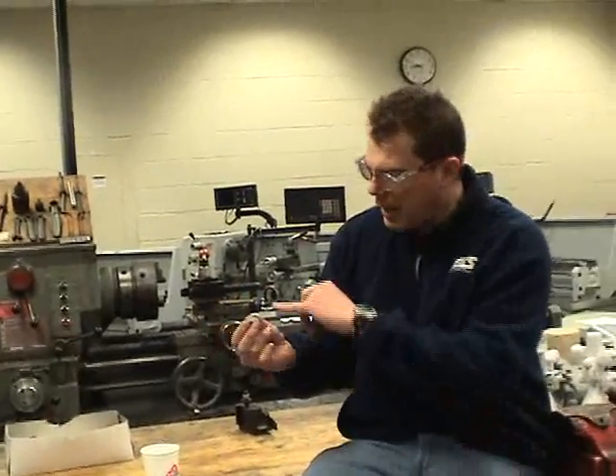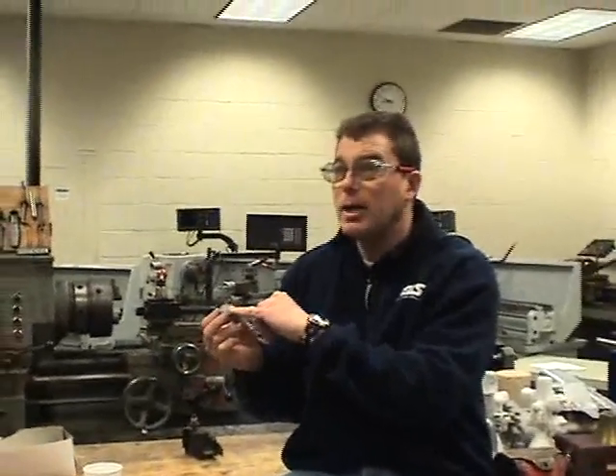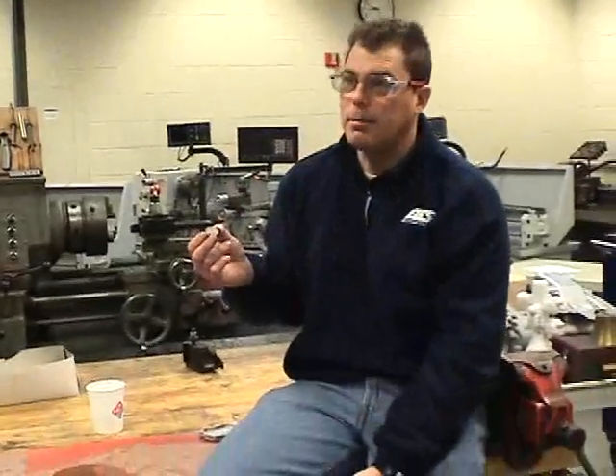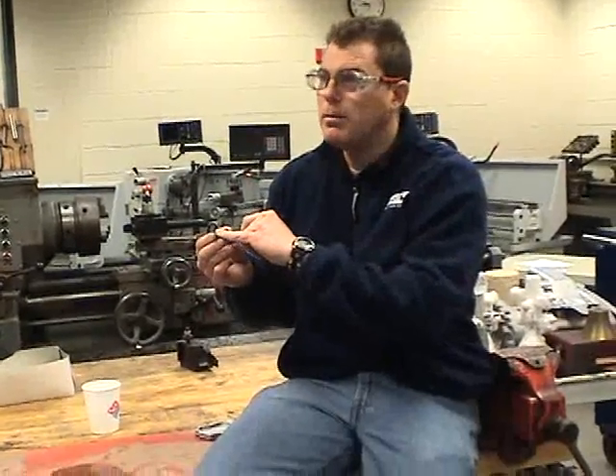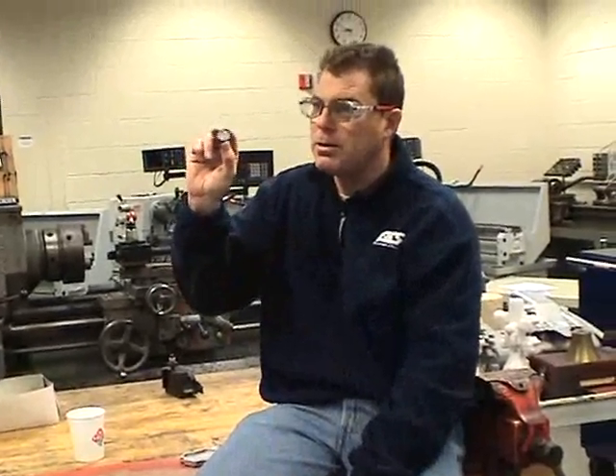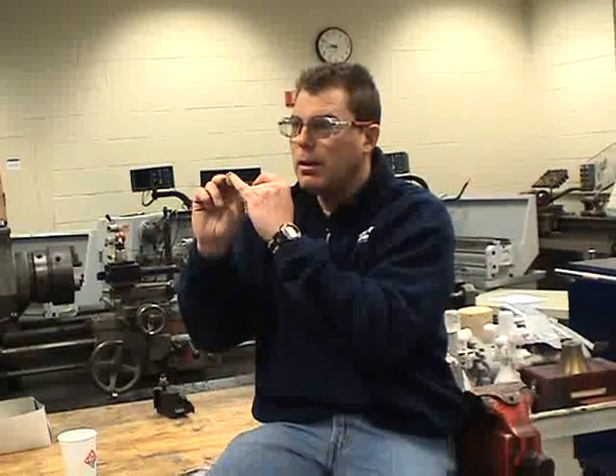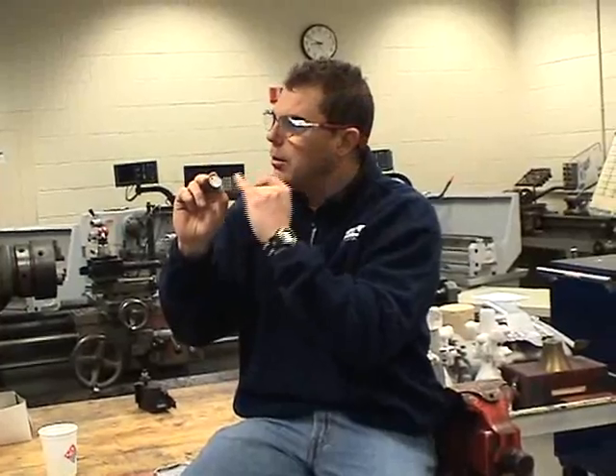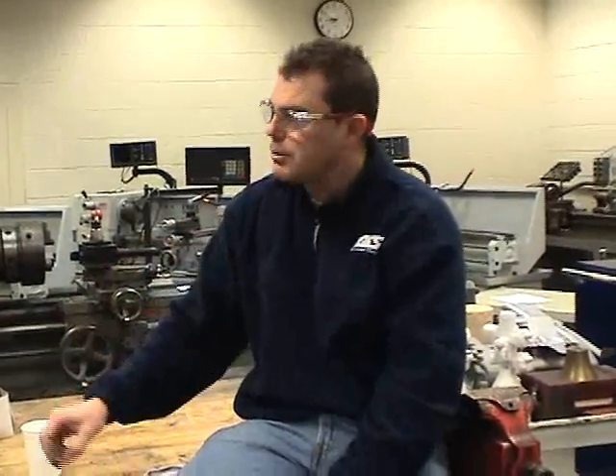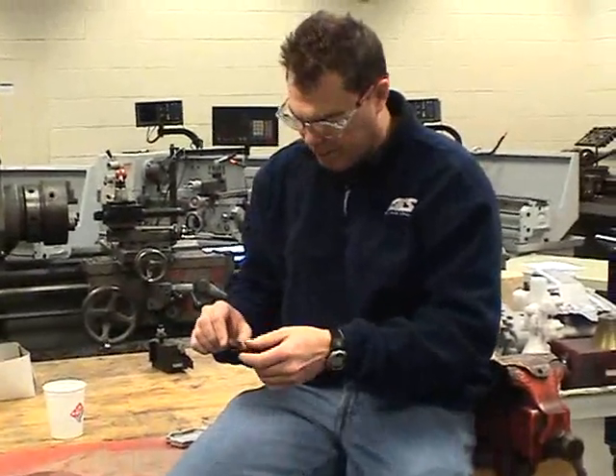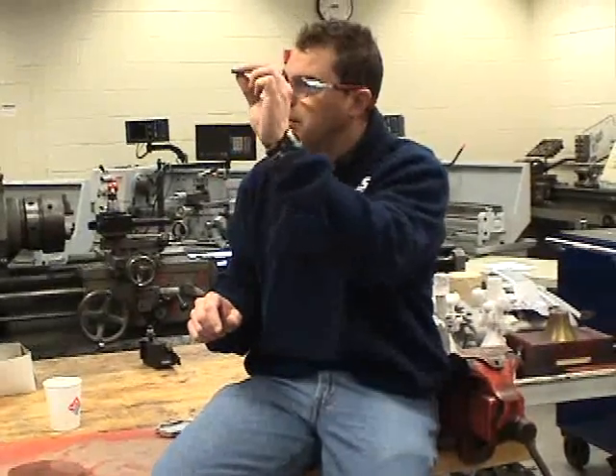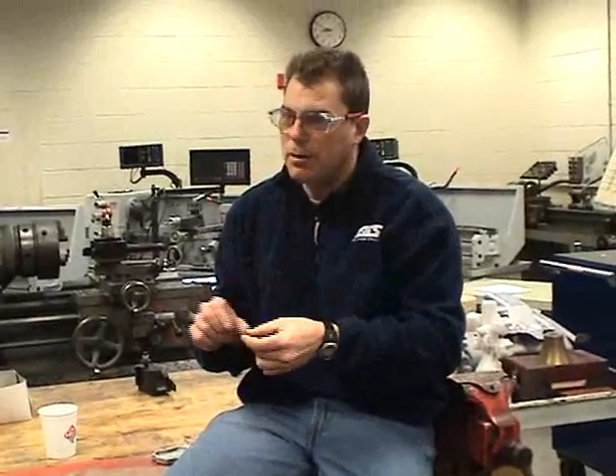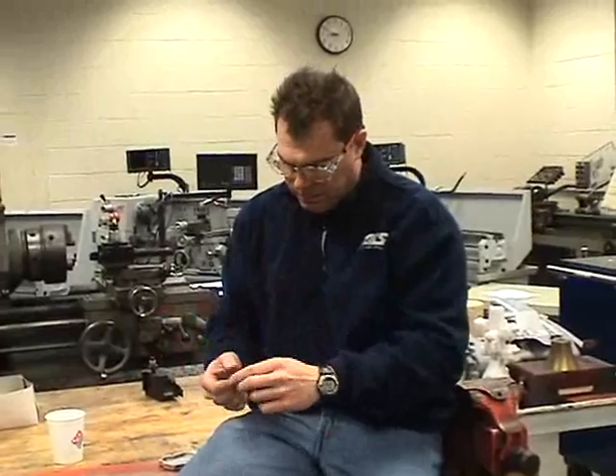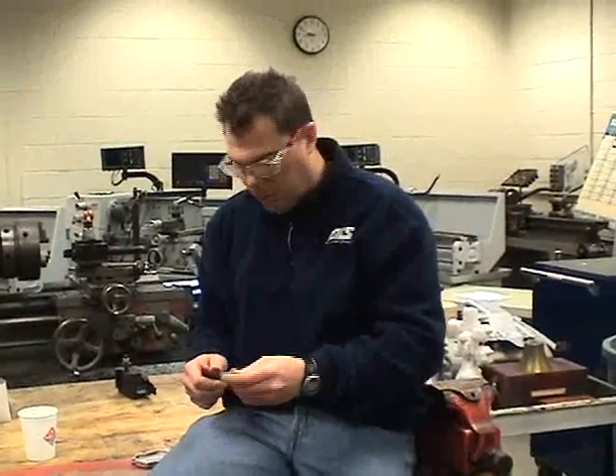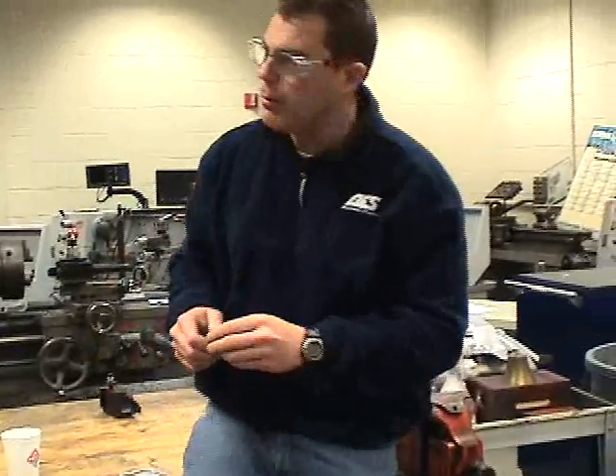What happens is, on the surface, carbon actually goes off and forms carbon dioxide. So you lose some carbon, and we're trying to determine the carbon content of this. So the hardness may vary slightly just on the very surface of it. If you get down a little bit, you're going to be better off. A little bit extra time on the sanding is not going to hurt you at all. I don't care if this ends up a few thousandths thicker or thinner at the end of it. That's not a big deal. Okay, so dry it off, and then we'll take it over to the